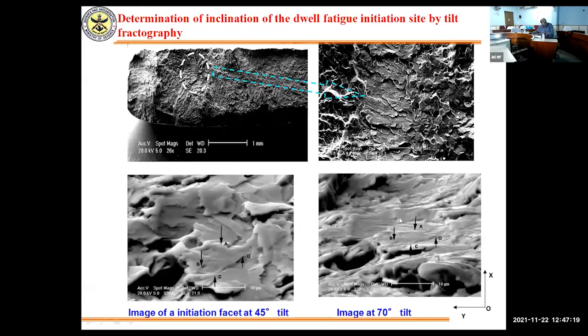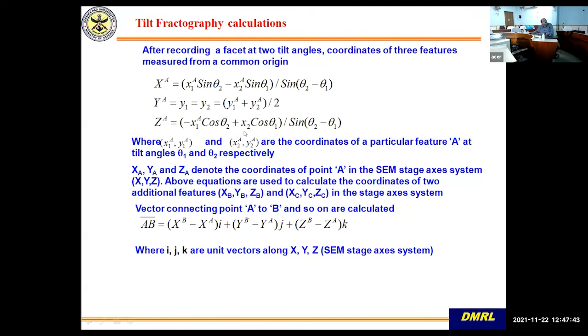Nowadays with EBSD and the SEM, you can see this is the flat specimen. The crack initiation region, which is the brittle region, is inside, not on the surface. And you can find out the physical orientation and also know the crystallographic orientation. It is possible nowadays. So you can do vector calculations, and you can plug it into this. These formulas are there. These are just vector calculations, nothing else. I'm not going into too much detail.